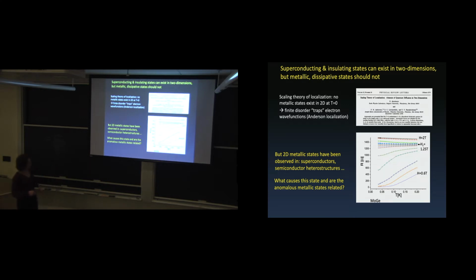And in fact, this is data that I took from my own thesis work. It was on a thin film superconductor, amorphous molybdenum germanium. There's resistance versus temperature. And you can see that as a function of magnetic field, at low fields, it basically goes to zero resistance. It superconducts. And at high fields, it's a weak insulator. But as you go in between, the resistance drops and then flattens out. So you see the resistance dropping and then seeming to flatten, which means it's not approaching zero. It seems to be approaching some finite resistance state.